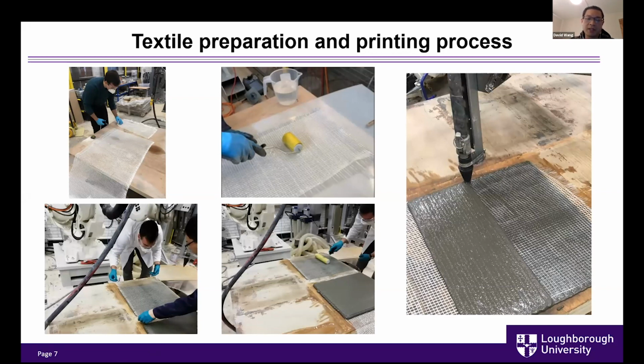After the first layer, or the bottom layer, of the concrete was printed, we manually place the coated textile onto the concrete. The fourth step is to apply a very slight pressure onto the textile to make sure the textile is well integrated into the concrete. After that, we will print the top layer of the concrete until all the printing is finished.